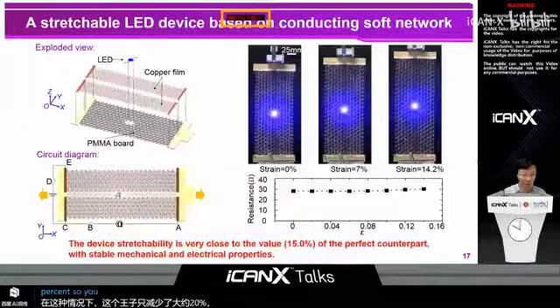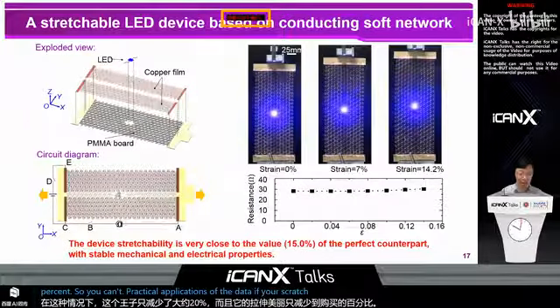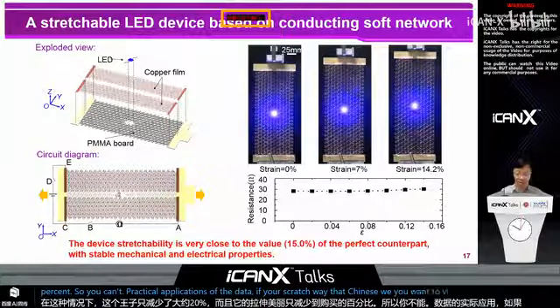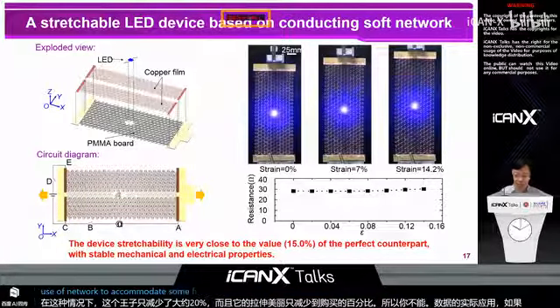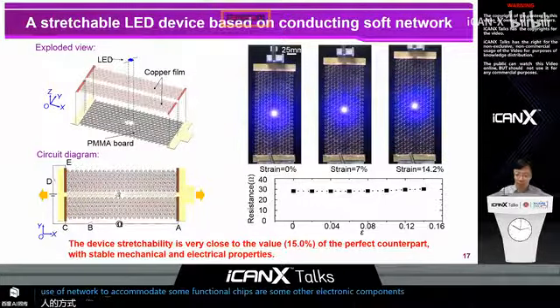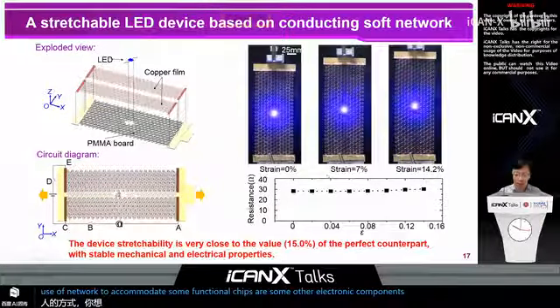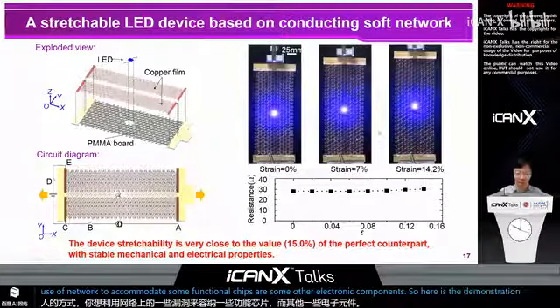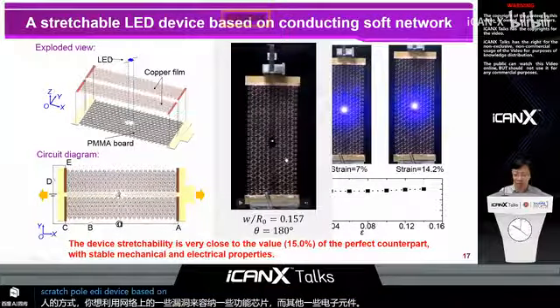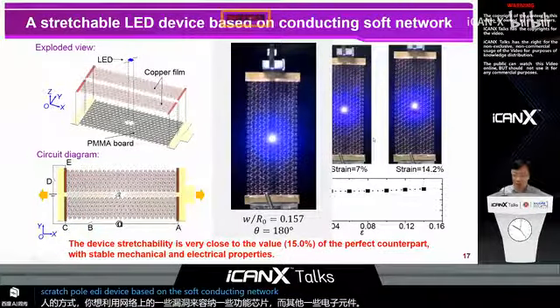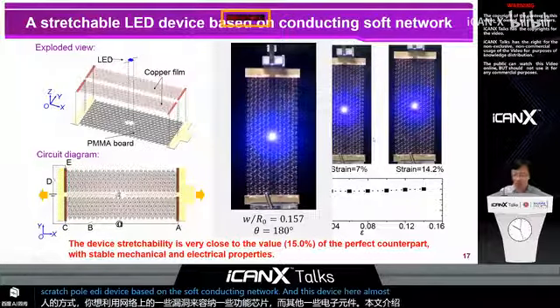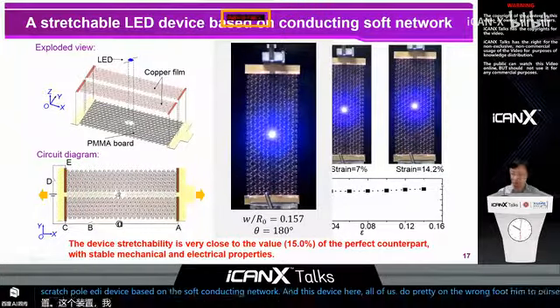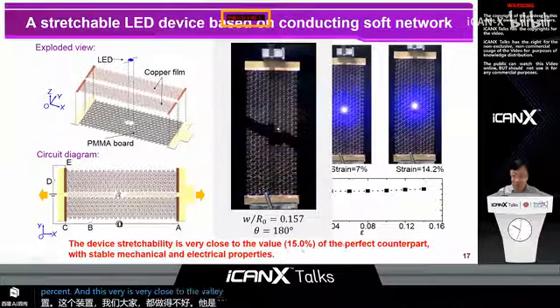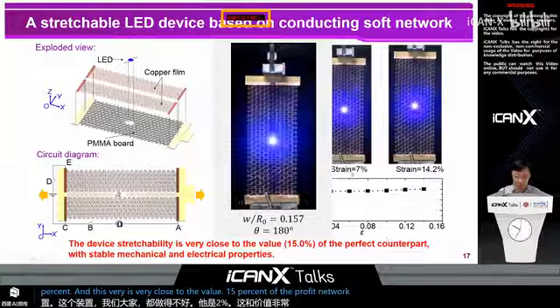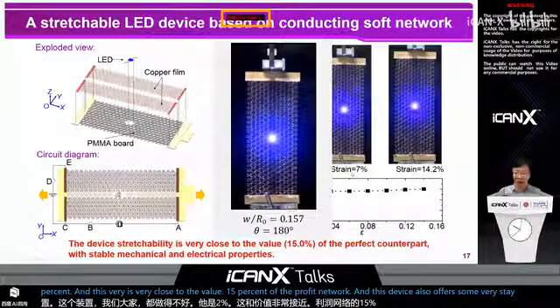So in practical applications related to stretchable electronics, we usually want to utilize some holes in the network to accommodate some functional chips or other electronic components. Here is a demonstration of a stretchable LED device based on the soft conducting network. This device can offer a stretchability of around 14.2%, and this value is very close to the 15% of the perfect network. This device also offers very stable mechanical and electrical properties.